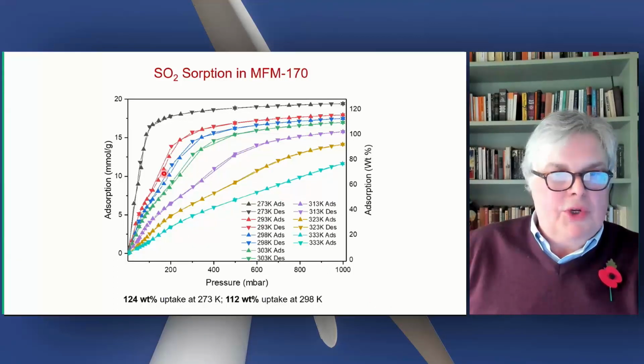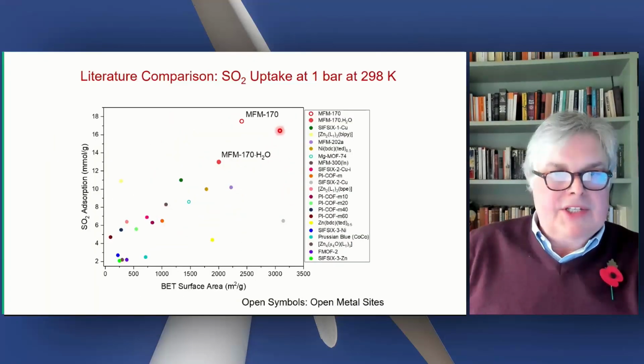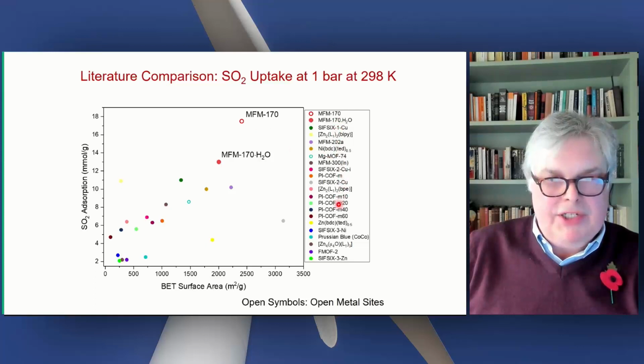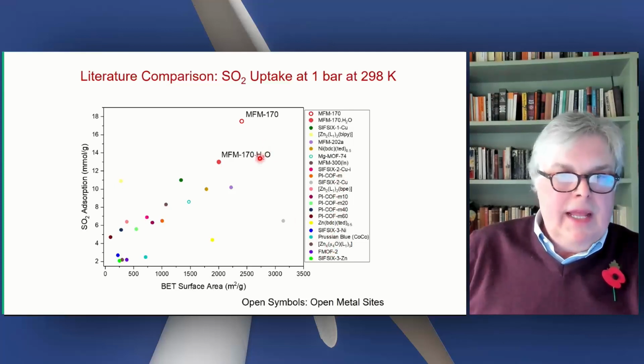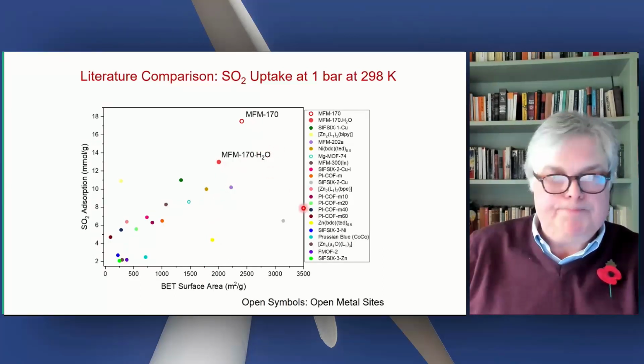It absorbs SO2 very effectively. These are the isotherms at different temperatures, and it's fully reversible. And in terms of the literature comparison, this has the highest SO2 uptake of any known MOF. There's a whole range of them listed here. Some of these are actually not fully stable to SO2, and you can only cycle a few times. Here is the hydrated version of MFM170. It has a smaller pore size. It, of course, has a lower BET surface area because the water takes up space.